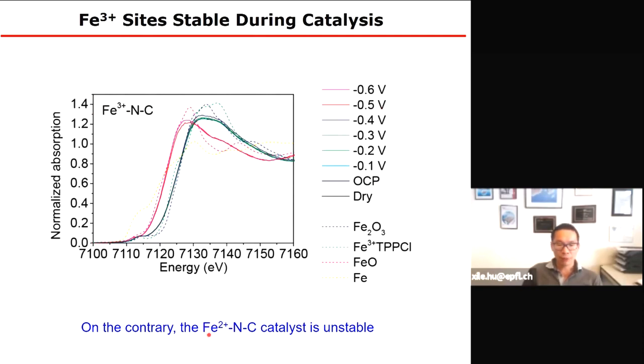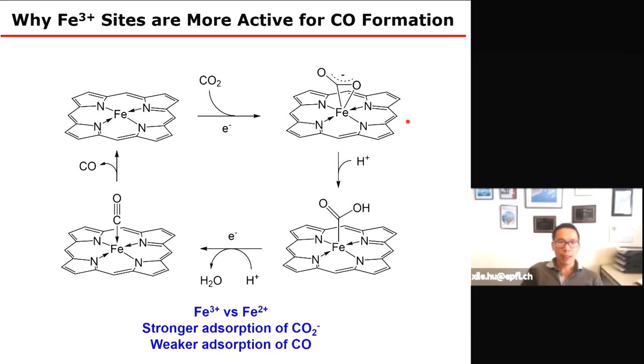On the contrary, if we use iron 2 catalysts, we found that the catalysts actually decompose very quickly under reductive potentials. And so that's unusual. And we think that the fact that we have iron 3 sites can explain why these catalysts are so active. Through mechanistic study, including electrokinetics, we know that the first step of this reaction is a proton decoupled electron transfer. So you make basically a CO2 radical adsorption on the iron site.